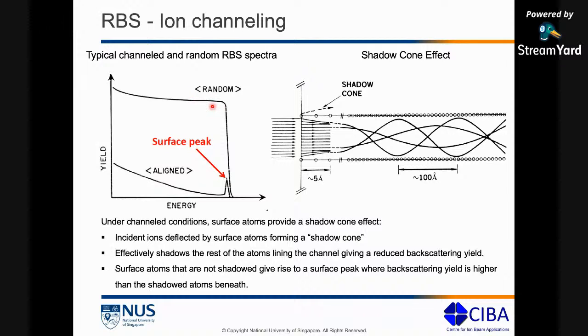And if we compare the random counts to the channel counts, this drop in the counts will give you an idea or an estimate of how good your crystalline structure is for your sample, for your silicon. Okay, if your silicon is perfectly crystalline, you will have a very good channeling effect. This difference will be large. That tells you that your crystal is of good quality. If your single crystal is not of good quality, your channeling will not be as good as this. So you will have your channel spectrum coming out from here, and then this difference will be smaller, which means your crystal quality is not good. Okay, so this gives you an idea as to how good a crystal you are working with. If you're able to get a very good channel spectrum, that tells you that your single crystal is of very high quality.